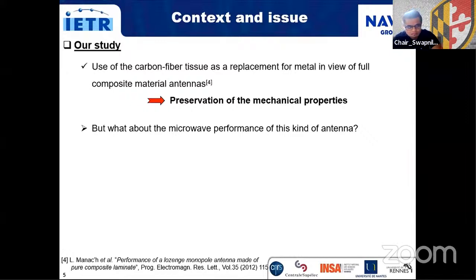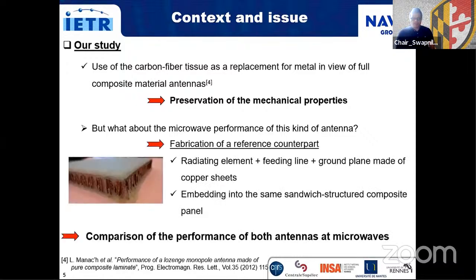Our study here concerns the use of carbon fiber tissue as a replacement for metal in view of the fabrication of full composite material antennas in order to preserve the mechanical properties of the composite panels. But what about the microwave performance of such antennas? We fabricate a reference counterpart with radiating element, feeding line, and ground plane made of copper sheets, all of which embedded into the same sandwich structure composite panel to compare the performance of both antennas at microwaves.